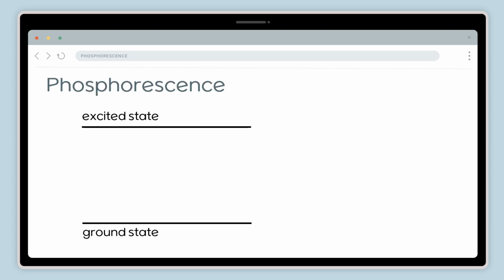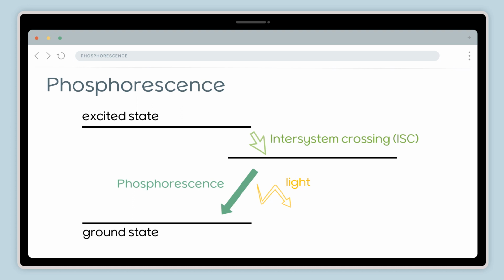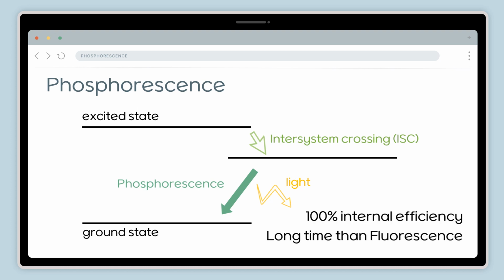Fluorescence uses only singlet, but phosphorescence uses both triplets and singlet. Heavy metals such as Ir and Pt complexes have large orbital and electrons of them are less affected by the central element. So, the excited state of S1 can be transferred to a state called T1. This process is called intersystem crossing, so the triplets make light emission by moving from T1 to S0. Phosphorescence needs a longer period than fluorescence, but it has almost 100% efficiency by using triplets, when fluorescence uses only singlet exciton.